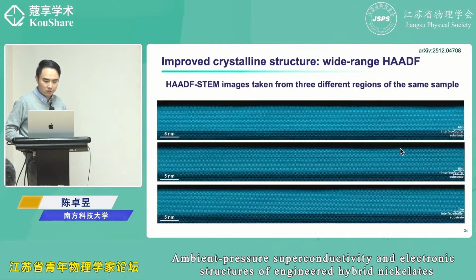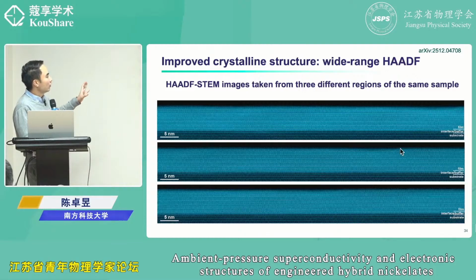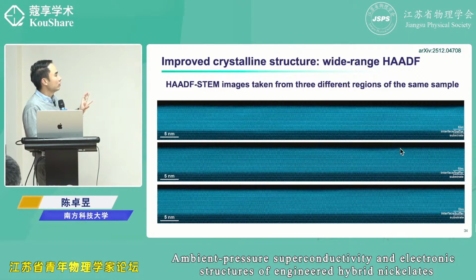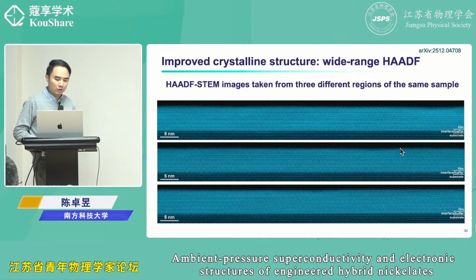So the first thing is the crystalline structure is greatly enhanced. These are 3 different regions of the same sample, TEM images. This field of view is the largest possible that you can still resolve atoms. If you use an even larger field of view, you can't see atoms. So using this largest field of view and taking 3 different regions, you can see these highly ordered cations and also an atomically sharp interface.